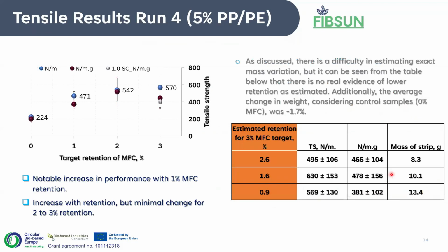So when we move forward and measure the tensile properties after MFC incorporation, we start with run 4, and what we see is the base control which was previously introduced. The tensile properties of the base control, and the tensile properties of the MFC incorporated at target retention 1%, and we see that already there is a substantial increase in these properties of the non-woven with MFC incorporation. From this result, what we notice is that at 2% retention, we already have some kind of optimum performance for this MFC. With 3% retention, we don't see any linearity in increase in terms of performance, especially when we normalize the result with the weight of the non-wovens.